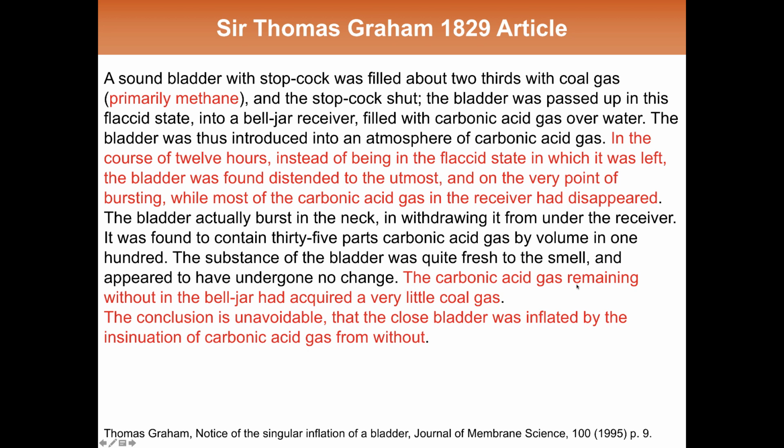On the other hand, the CO2 that remained in the bell jar had acquired very little of the methane or the coal gas. And the conclusion is unavoidable that the closed bladder or sealed balloon was inflated by the insinuation or the permeation of carbon dioxide gas from outside. That is, the CO2 would permeate into this balloon faster than the methane would permeate out. And so the balloon would actually inflate itself.